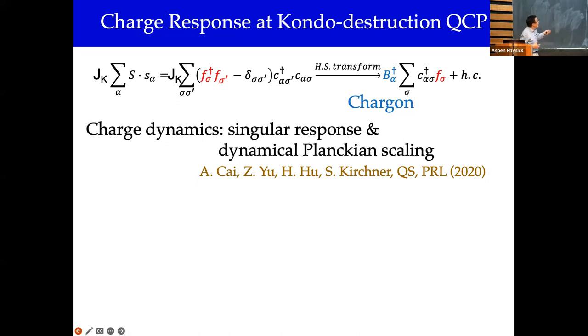So I have one more slide. I'm lying, two slides on this part of loss of quasiparticles, which is that in the Landau description, if I have an antiferromagnetic or some magnetic order state to a paramagnetic phase transition, the only criticality I expect to see is in the magnetic sector, which is why the neutron scattering measurement of spin dynamics plays such an important role for this class of materials. But if it involves this Kondo effect, in fact, the history of the Kondo effect was a mystery in the 1930s, that electrical resistivity versus temperature was showing some strange minimum. So the electrons have charge, which are coupled to the spins. So the charge sector actually is involved.